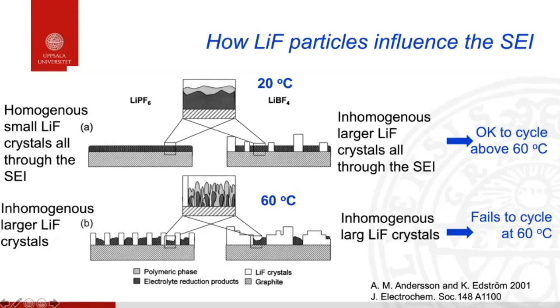If you have a fully lithiated graphite, lithium will just go out. You can see that this was made in 2001. So we can also see from the studies we did then, it was very much based on microscopy and XPS studies, that this lithium fluoride layer was sort of small crystallites all through this organic layer. So it was not just a layer close to the surface. So it was sort of spread out. And that was lost with the other one.